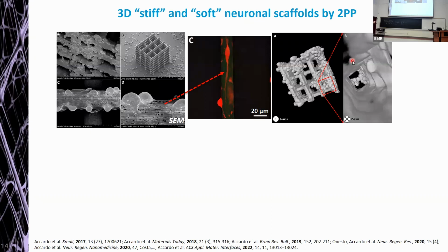This is actually a light sheet fluorescence microscopy 3D reconstruction of the scaffold, where you can actually recognize the cells colonizing the inner beams. One of the most interesting things is that by using the high resolution of 2PP, I was able also to decorate the cylinders of this woodpile structure with some nanogratings, which acted as guiding pathways for the alignment of neuritic extensions. Very nice proof of concept. But again, the limitation here was the material and the fact that we were using structures which were still pretty thick.